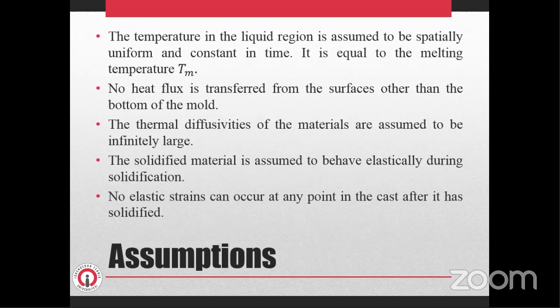The temperature in the liquid region is assumed to be spatially uniform and constant in time. It is equal to the melting temperature Tm. No heat flux is transferred from the surfaces other than the bottom of the mold. The thermal diffusivities of the materials are assumed to be infinitely large. The solidified material is assumed to behave elastically during solidification. No elastic strains can occur at any point in the cast after it is solidified.